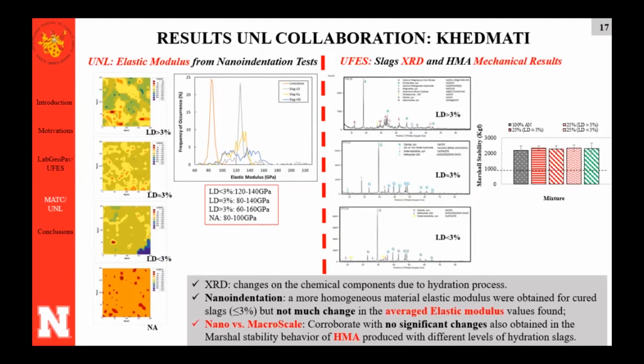So the XRD shows the change in chemical components due to the hydration process. The nano-indentation shows a more homogeneous material elastic modulus when we had cured slags with level of expansion lower than 3, but not much change in the average elastic modulus. So comparing the nano-indentation results with the macro scale results, they kind of corroborate with each other, with no significant change on the Marshall stability, because we didn't have much significant change in terms of the average elastic modulus.